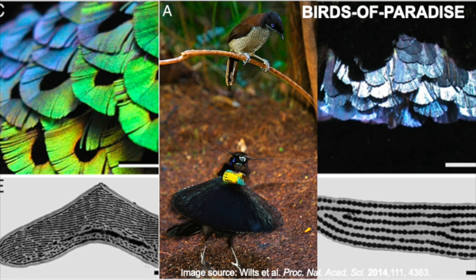In Lawes's Parotia, the occipital, nape, and breast feathers exhibit distinct nanostructures. The barbules in both regions contain well-ordered layers of melanosomes embedded within a keratin cortex, but with markedly different morphologies. Occipital feather barbules are flat and contain melanosomes of approximately 250 plus or minus 20 nanometers in diameter, with an interlayer spacing of about 400 plus or minus 20 nanometers.